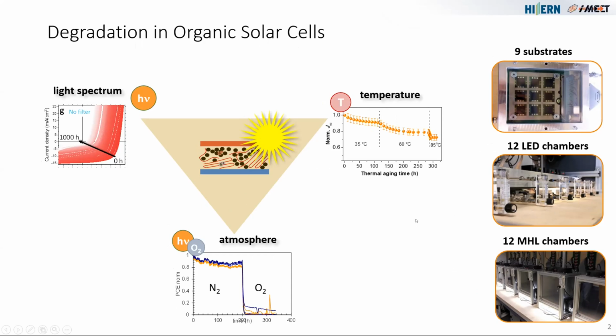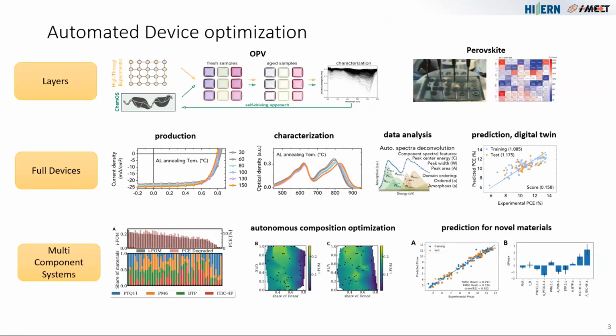And now, when using the robot technologies that Jared and Chris have been developing at HIERN together with Stefan Langner, we basically did go through a certain evolution in terms of what we were doing. We first started together with Stefan Langner to mix different OPV active layer materials together. We then drop casted films. Then we degraded those films in air and measured the photo bleaching effect.